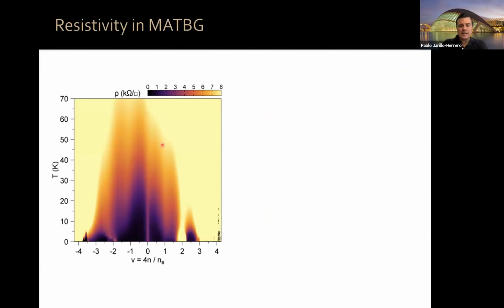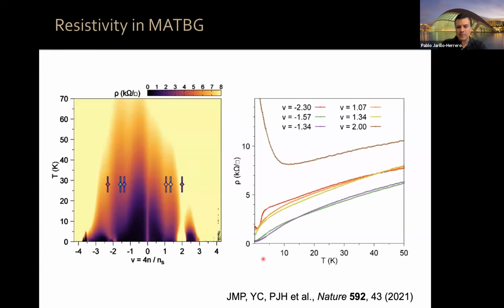In this device, we can measure the resistivity as a function of temperature all the way up to 70 Kelvin. This is resistivity for selected traces here. You can see that near nu equals 2, where the correlated insulator state is, it is very linear. You can see it's perfectly linear, down to a temperature at which the correlated insulator takes place. Then we go to regions nearby where the resistivity goes down because it's in proximity to superconductivity, etc.